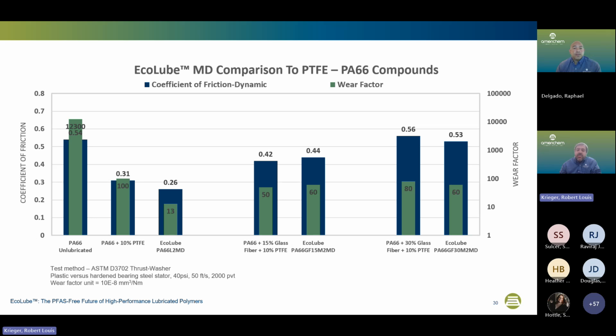On the left side axis, you show the dynamic coefficient as the blue bars. And on the right side, you show the wear factor on the green bars. And you can note the very close parity in both the wear and friction between the PTFE containing and the EcoLube grades. So you're comparing this one to this one, these two, 10% PTFE to our EcoLube offering.